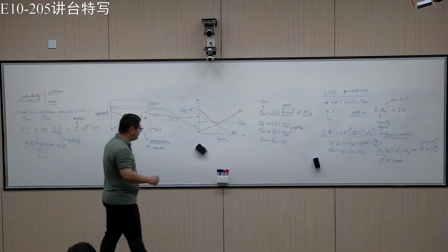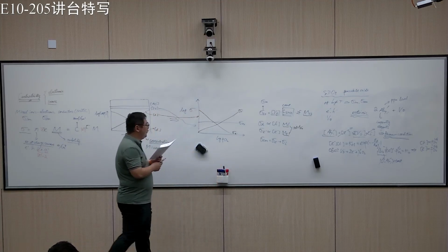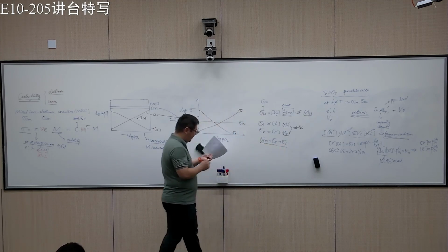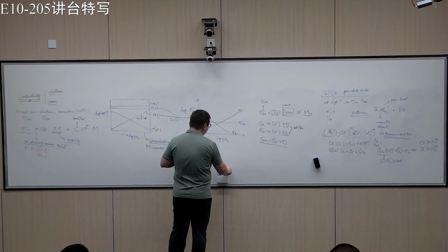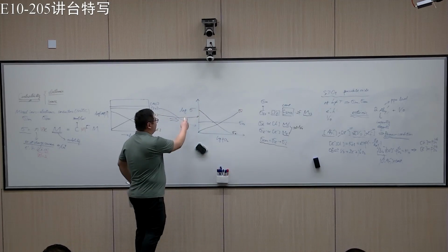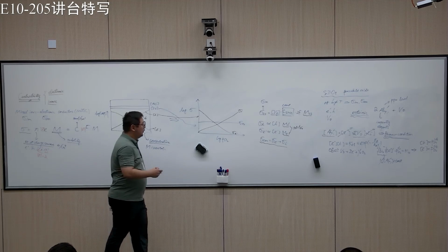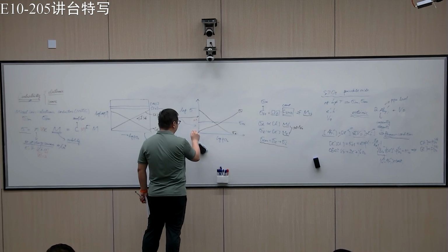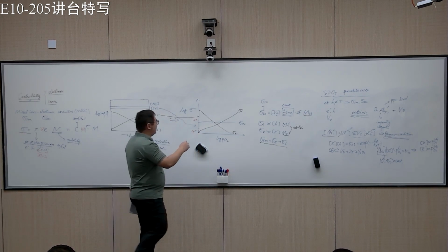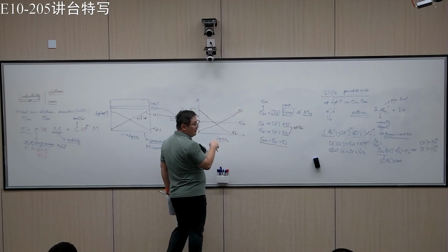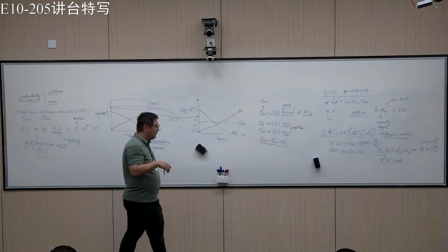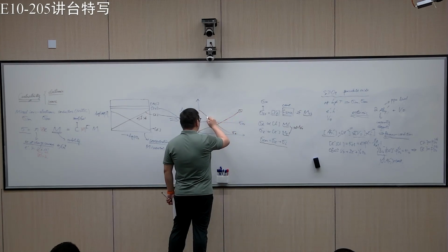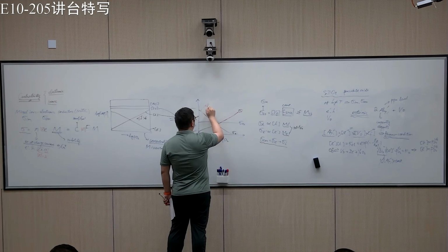So of course, when you measure electronic conductivity, we will measure this one. So this is the summation of these two, right? So if you plot that one, remember this is log sigma, okay? So which means that it could be 10 to the minus 3 here, could be 10 to the minus 5 here, right? So which means that the electronic conductivity will follow the one with higher conductivity. Will basically follow this one. So this is your electronic conductivity.